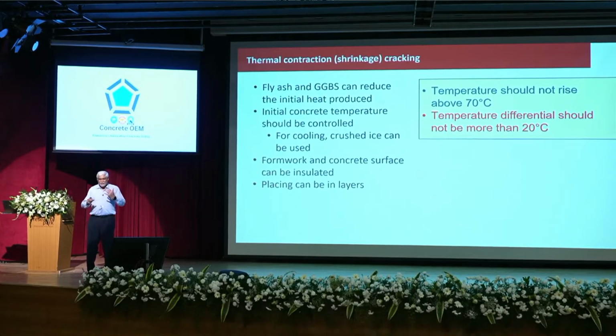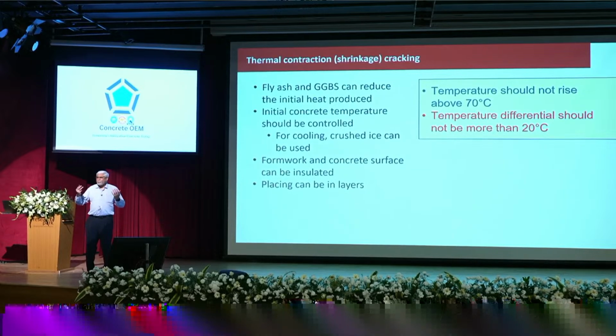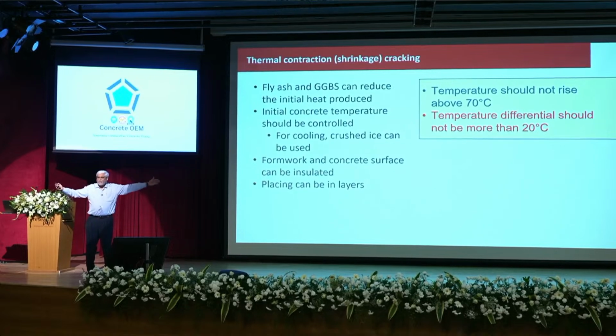What we generally say, I know that somebody here is going to say that these numbers are over-conservative. If somebody comes to me, and that is why most people don't come to me, when there is an issue of thermal cracking, I would say internal temperature should not be more than 70 degrees. Okay? And the gradient between outside and inside should not be more than 20 degrees. There can be exceptions. We'll discuss case by case when the case arises. But in general, the inside temperature should not go more than 70, because much beyond 70, concrete starts drying up, you have changes in the microstructure. And if there's a big gradient from inside and outside, the outside cools faster, and to accommodate the contraction, it cracks. So thermal temperature and heat is very, very important.